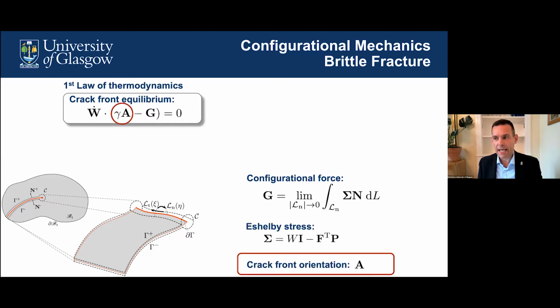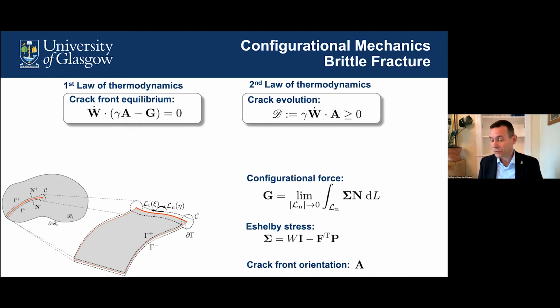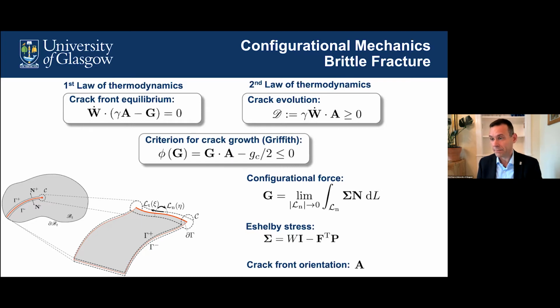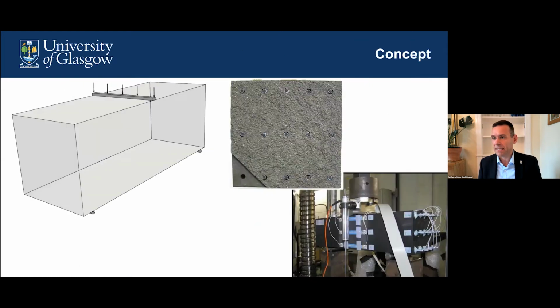And the resistance to that configurational force is the material resistance, which is given by the fracture energy and this kinematic variable A, which describes the crack front orientation. So this gives us an expression for equilibrium of the crack front. We also exploit the second law of thermodynamics, which defines the crack evolution. And all of this is supplemented then by a criterion for crack growth based on Griffith's criterion.